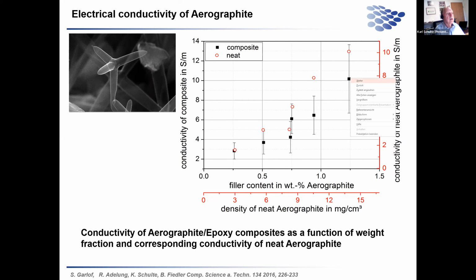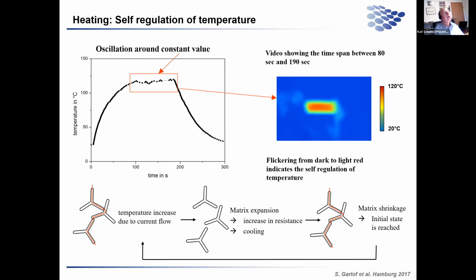What you can now do with it: we have a material that is conductive, so you put electric current on it, the nanocomposite with aerographite, and it heats up. You have an increase in temperature, and then you can hold it there because you have an electric path maintaining the current flow. What happens is it gets overheated, and due to the overheating, it expands. The contact points are interrupted, it cools down, and then you wait. It cools down, contacts reconnect, and it heats up again.